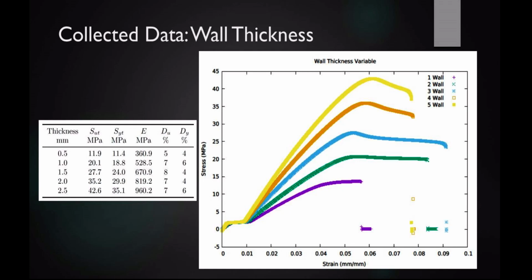But we do see some pretty interesting effects in the stress strain curves. We start off with a very characteristic, a very polymer-like start to the stress strain curve, with actually a microstructure property showing through in our final structural form. Most of what we're looking at is structural, in terms of the infill shape, how these things are actually being printed. But this toe region here is actually a polymer property where you have these microstructures unfurling to align with the load and actually lock in place once they're there.